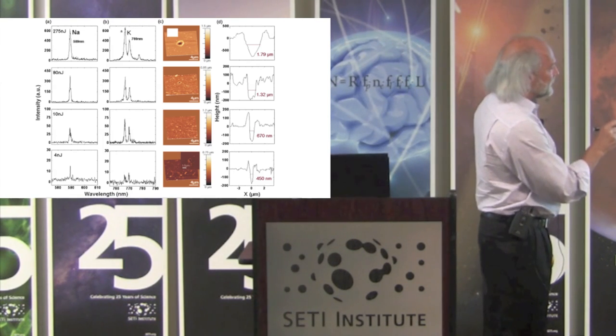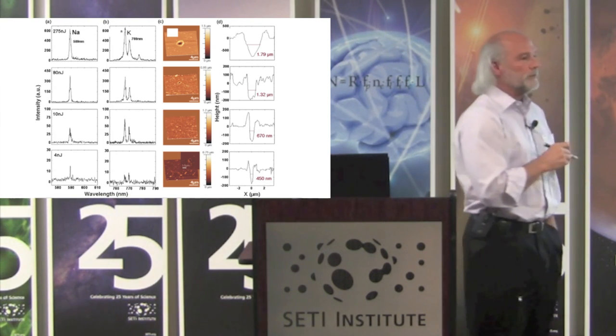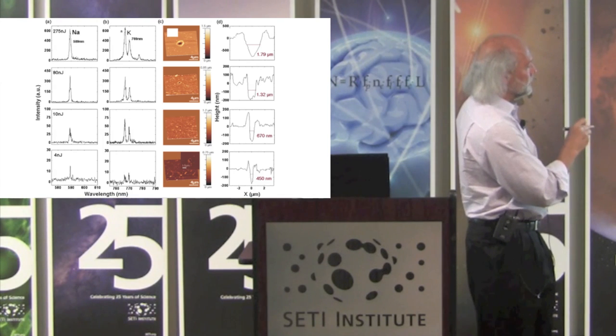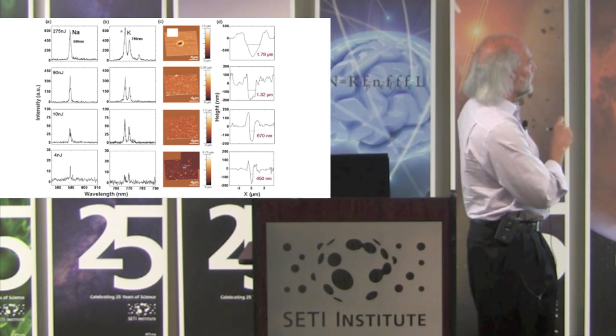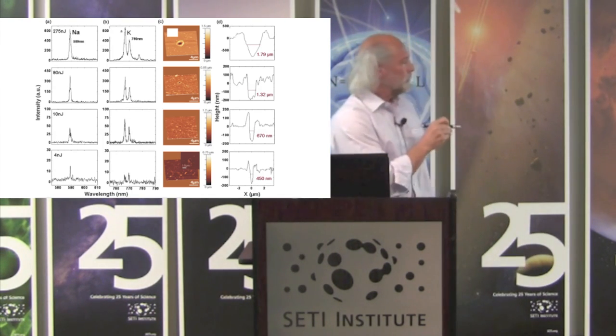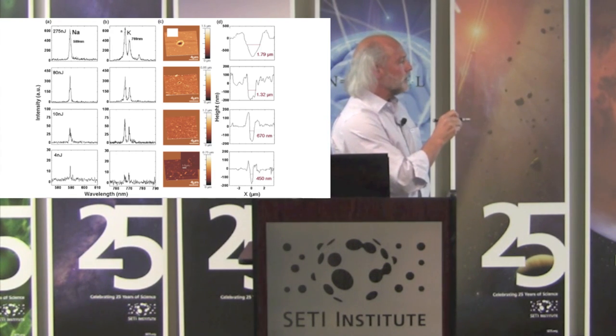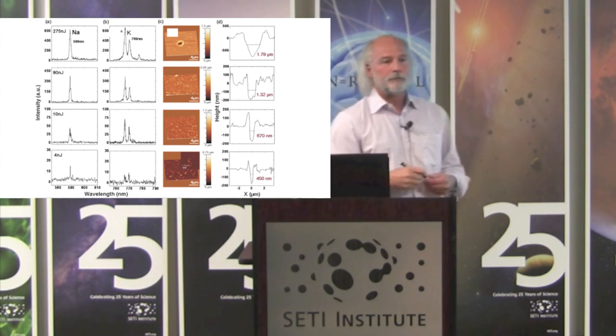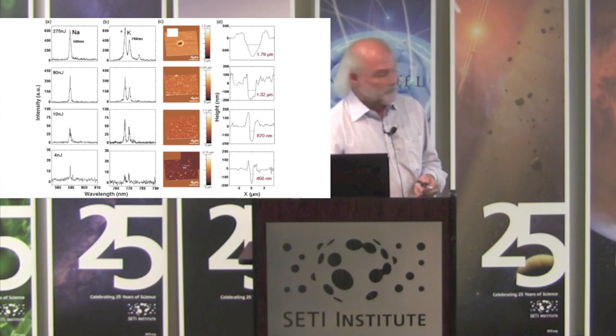At this spot, there's our spot size. It's on the order of about 450 nanometers, and we are seeing signal. So there's the potassium lines, there's the sodium line. So we're doing LIBS now, single laser shot, with a spatial resolution of 450 nanometers diameter.